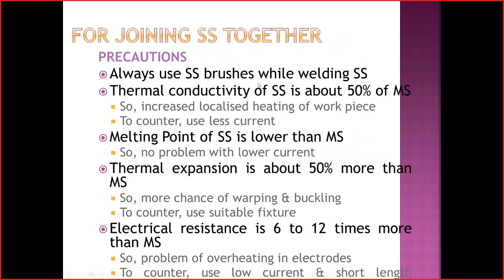And always use SS brushes. Several times I have repeatedly told you we have to use SS brushes only. Thermal conductivity is less, which increases localized heating of the workpiece, so to counter it use lower currents only. I also repeated that the melting point of SS is lower than MS, so there is no problem with lower currents. Thermal expansion is also 50% more than MS. There is more chance of warping and buckling. So use suitable fixtures. For longer joints, better go for fixtures to get good welding.